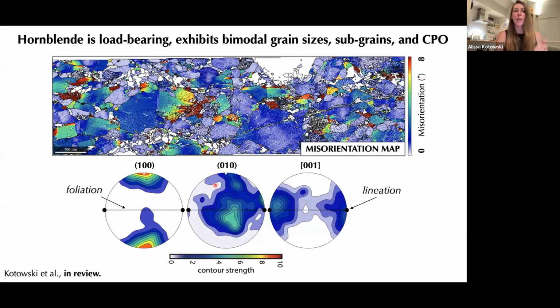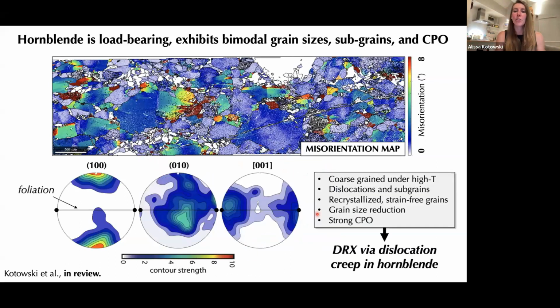And this is also consistent with this figure on the bottom, which is a pole figure. So what this is showing you is the poles to certain crystallographic planes and directions. And the only important thing to think about from this is that the fact that we see clustering of the poles to certain planes and directions means that there is a systematic preferred orientation of the hornblende in this rock. So we have certain specific alignments of the 100 poles perpendicular to the foliation, and for example, 001 directions aligned parallel and contained within the lineation or defining the lineation. So all of these observations are consistent with the interpretation that hornblende in this rock is deforming by dynamic recrystallization accommodated by dislocation creep.